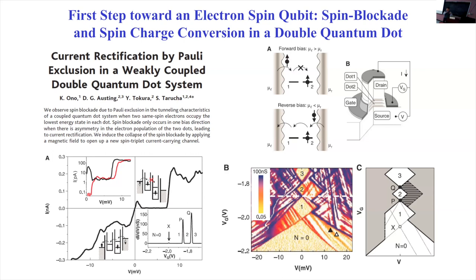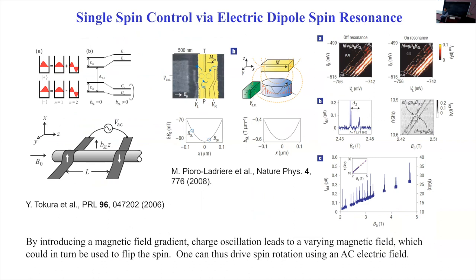So instead of directly measuring the magnetic signal using a SQUID, now you can do a charge measurement, which can be much more easily done. So that was, I think, really an important experimental development that allows single electron spin measurement. And no matter whether in gallium arsenide or silicon, it turns out the spin orbit interaction is not that strong. So there's always a question of how do you flip a single electron spin. As I mentioned, the original proposal was just using the traditional ESR: using a DC magnetic field to split the spin levels, the qubit, and then introduce a transverse AC magnetic field to flip the spin, right? That's the typical electron spin resonance protocol.